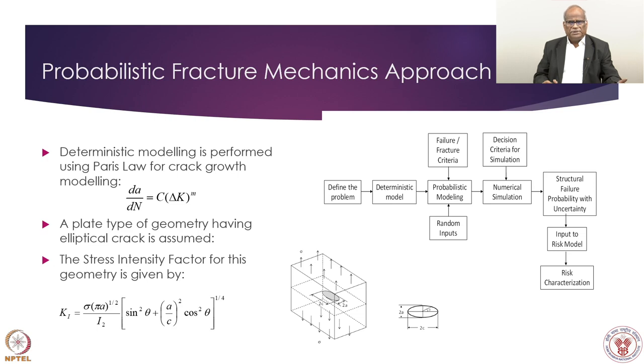Now, if you look at the probabilistic fracture mechanics approach, basically we use the modeling part, that is Paris law. This is a deterministic model. Basically, it relates the crack size and number of cycles to determine the rate of crack growth, and this is related to the stress intensity. So we can see here dA by dN, where delta K is the change in the range of stress intensity, and m and C are material constants.